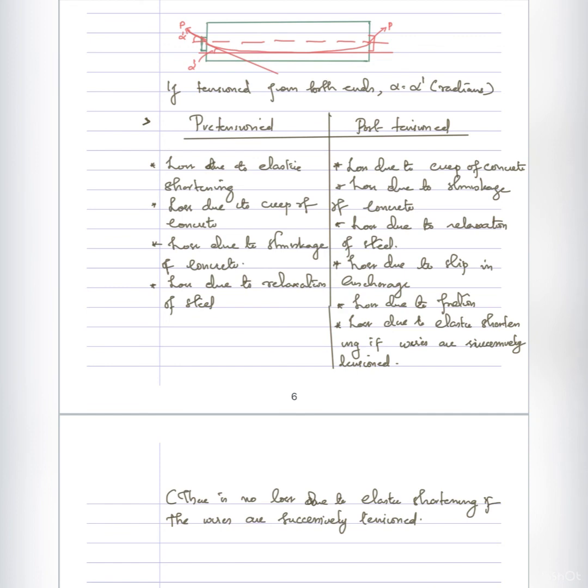There is no loss due to elastic shortening in post-tensioned members when tensioned simultaneously. In pre-tensioned members, the losses are: elastic shortening, creep, shrinkage, and relaxation of steel — four types. In post-tensioned members, the losses are: creep, shrinkage, relaxation of steel, anchorage slip, and friction. The elastic shortening loss applies to post-tensioned members where wires are not simultaneously tensioned.